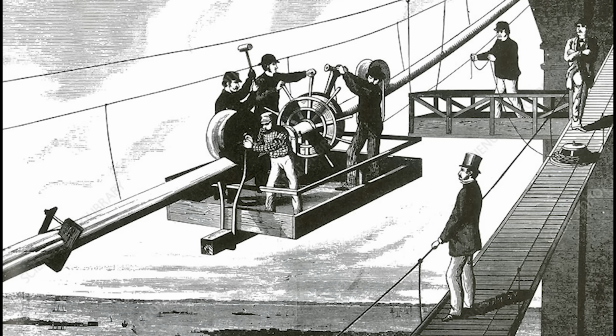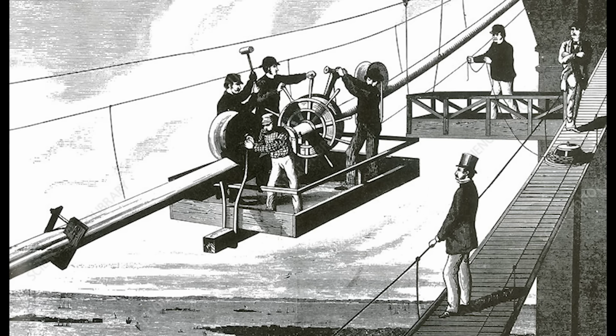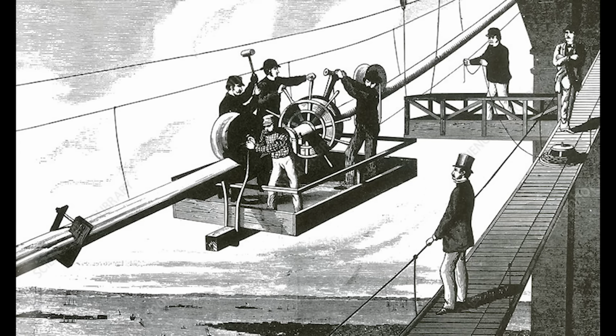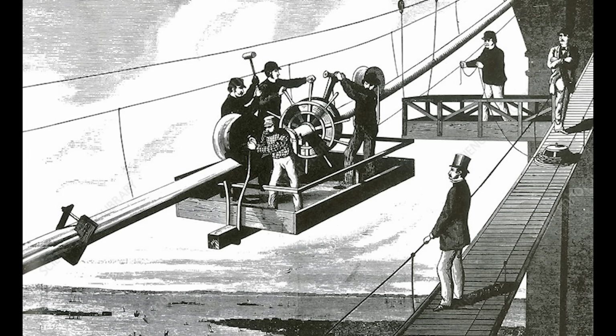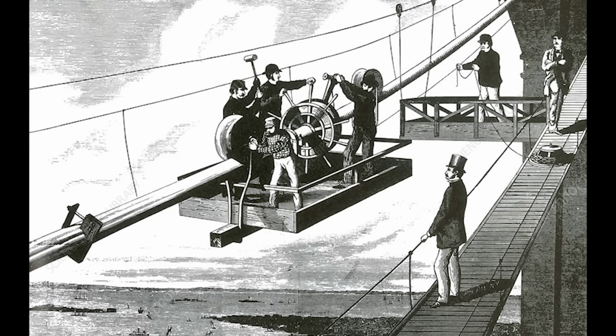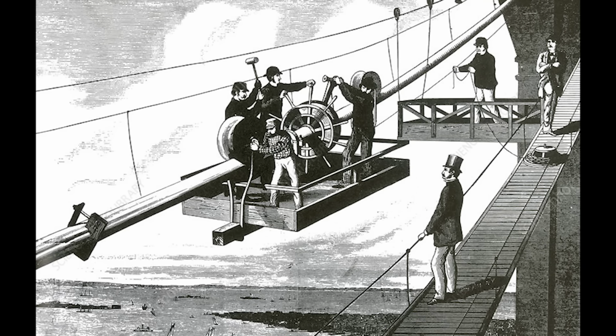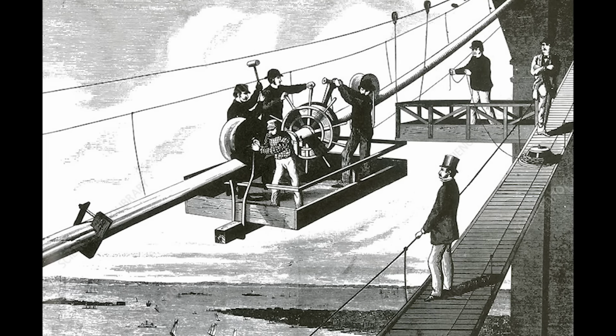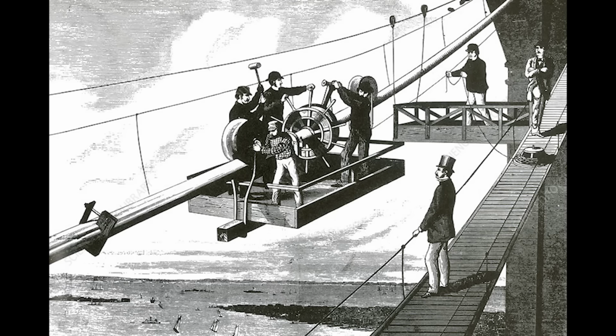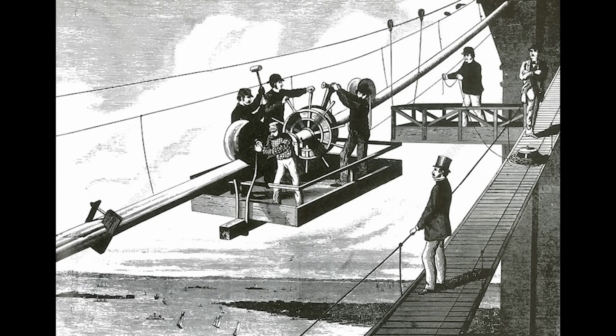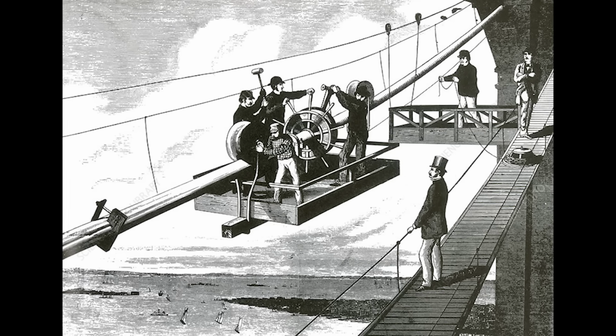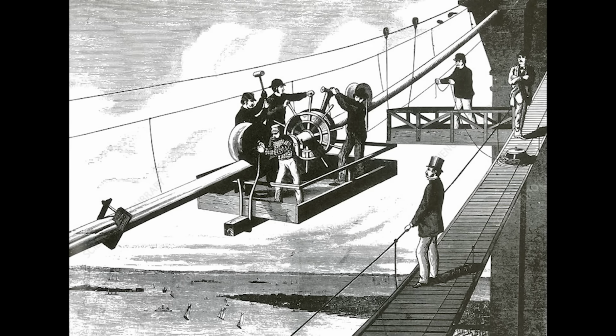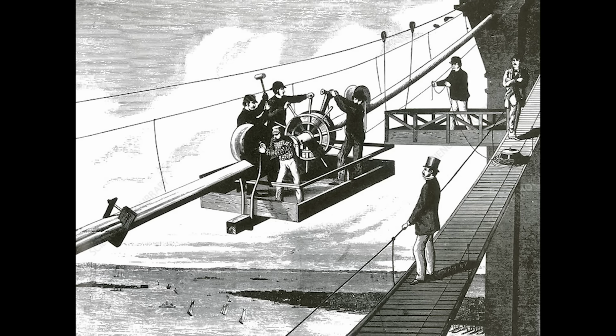The spinning operation began with mechanical precision that impressed even the European observers who had come to witness American engineering methods. The traveler system carried wire across the completed span in continuous loops, building each cable strand by strand through thousands of individual passes. 4 wires traveled with each crossing, and workers positioned them according to patterns that would create a circular cross-section when compaction began. Roebling watched through his telescope as the traveler made its methodical journey from Brooklyn to Manhattan and back. The system eliminated the need to splice short wire segments into longer cables, creating continuous steel strands that ran the full distance between anchorages without breaks that could concentrate stress or trap moisture. Each wire maintained its galvanized protection from anchorage to anchorage, a single piece of protected steel contributing to the cable's collective strength. The compaction process required different mathematics.